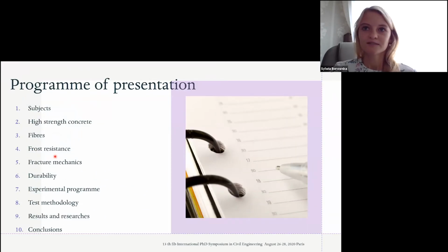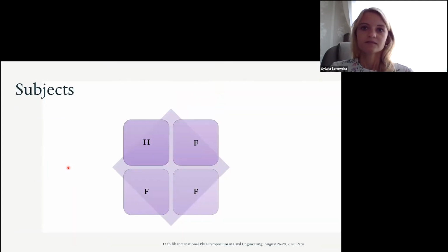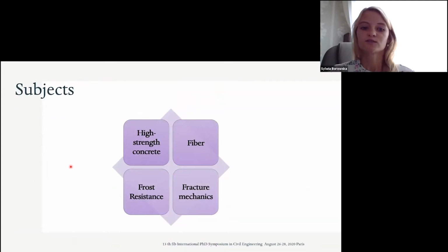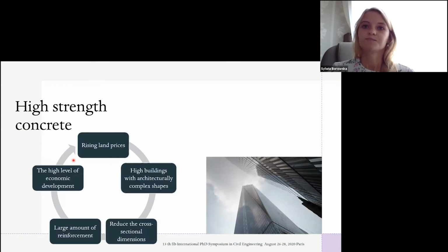My presentation is structured as follows. The aim of the presentation is to describe frost degradation of high-strength concrete by compressive strength change, mass loss, and durability factor change, and then to compare with the modification of stress intensity factor, fracture energy, and crack mouth opening displacement after 150, 250, and 350 cycles of freeze-thaw.